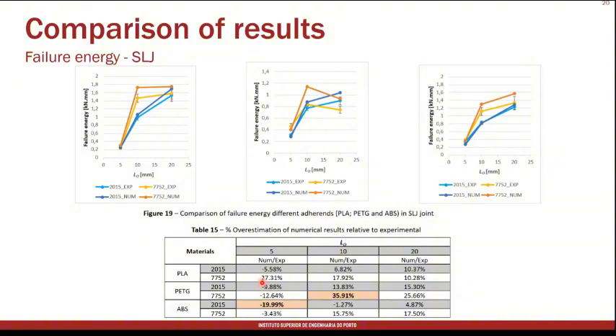P-delta curve. So it gives us an idea of the dissipated energy before failure. And if we begin by the single lap joint, we can see that we have a significant increase between 5 and 10 millimeters, which is consistent with the increase in maximum load and also with the increase in the failure load, but between 10 and 20 millimeters, the alteration is minimal, and in some cases we actually have a short reduction because the specimen gets more brittle.